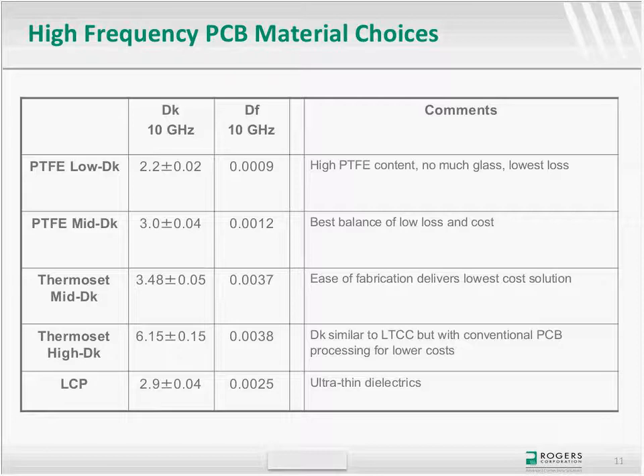The one thing that happens here is now you go up a little bit in the loss of the materials. The loss tangent starts going up a little bit, and also the dielectric constant value does go up and move away from just being a pure PTFE resin, which itself is around 2.1 dielectric constant.